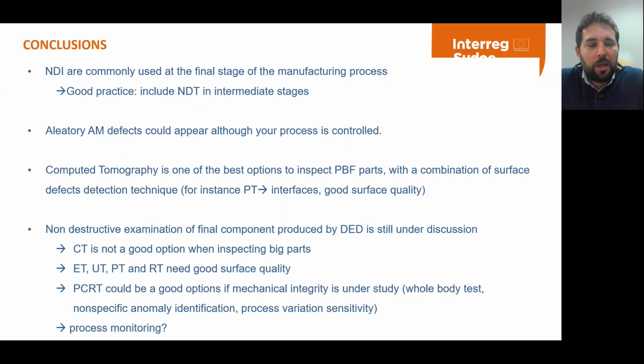So finally, some conclusions. Non-destructive inspection is commonly used at the final stage of the manufacturing process, although it's a good practice to include this testing in intermediate stages, saving cost, for example. Although your process is controlled and closed, aleatory AM defects could appear. It's something that you have to take into account. That is why the non-destructive testing is still important at the end of the process before delivering the part.